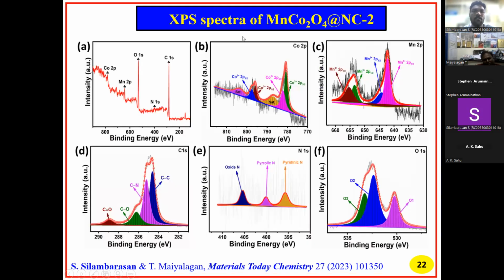Next, the XPS spectroscopy of MnCo2O4 at nitrogen-doped carbon. In the XPS, we confirm the elemental composition and valence state. Figure A is the survey spectrum. The cobalt 2p, manganese, oxygen, nitrogen and carbon, all these elements are confirmed in the XPS survey spectrum. Figure B is the cobalt 2p, which has +2 and +3 oxidation states.